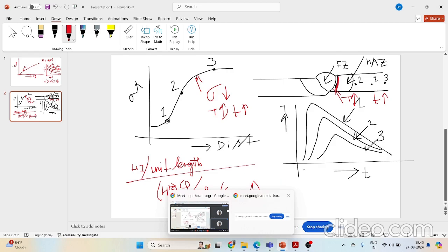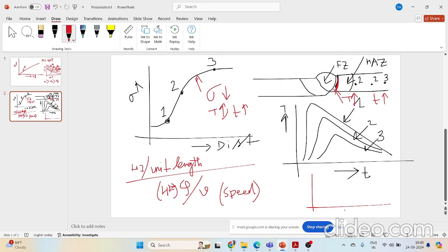Now, if I want to plot this grain size, how will it vary? So this is my distance, the x-axis is my distance, and let's say this is my grain diameter or grain size. Which location will experience the maximum grain size? The location which is experiencing more temperature and time above recrystallization temperature. As simple as that. So my location 1 will experience the highest grain size compared to location 2 and location 3. As you approach the base metal region, I will end up with a much finer or much unaffected region, right? As you increase time and temperature, you are enhancing something called grain coarsening. Correct?